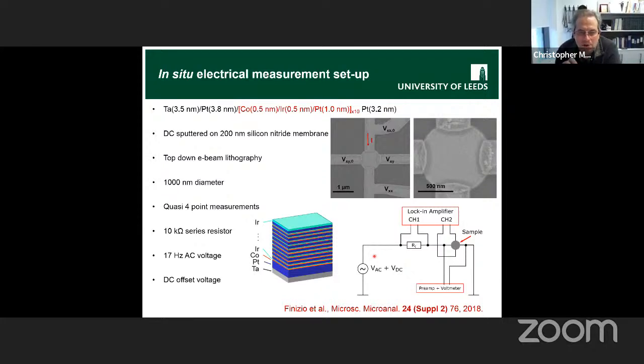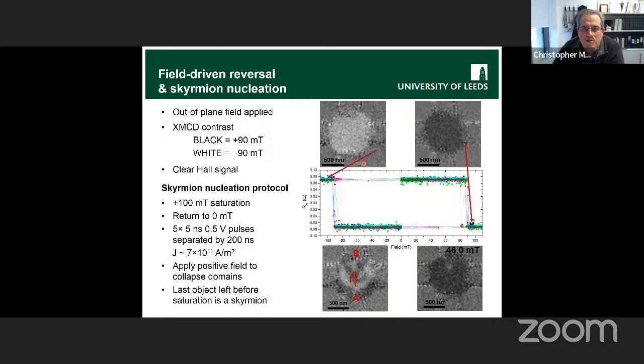So the way we went about this was, again, we were in the microscope in Switzerland. We have our disk of multilayer. It's platinum, cobalt, iridium again. We've got Hall contacts, and we can look at it in the microscope, and we can measure in the microscope. So every time we make a Hall measurement, we can image the spin texture that's given rise to that signal. This was actually before a microscope upgrade. So you're now used to looking at good images, and these are a little bit rougher. But here we've got our disk, 1 micron disk, saturated up, saturated down, bright and dark. We can get domain patterns inside it. And here's a single Skyrmion, a little patch of bright contrast in a dark background.